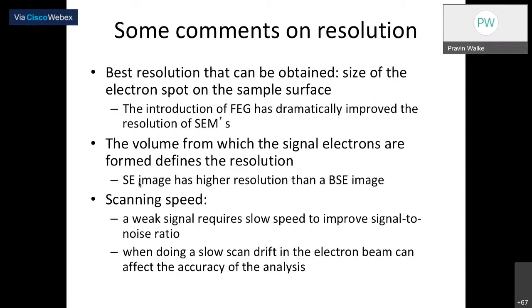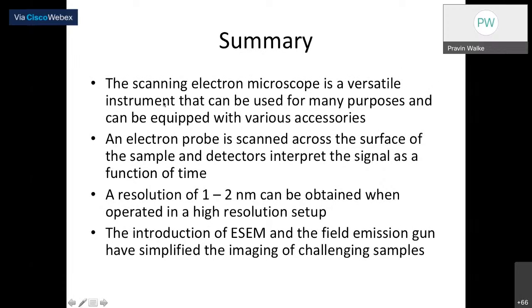Another important factor in the resolution is the scanning speed, right? A weak signal requires a very slow speed in order to improve the signal to noise ratio. But when we are doing a very slow scan, we can observe drift in the electron beam over fractions of milliseconds, and that will definitely affect our analysis. So these are the important factors to keep in mind about electron microscopy.